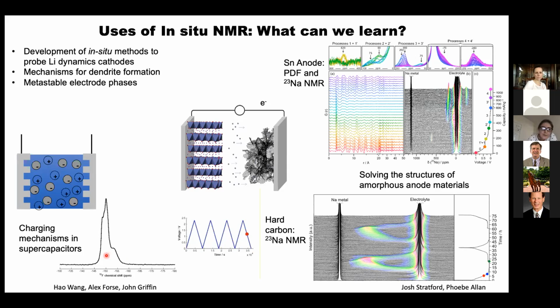And then you can also see that the peaks shift backwards and forwards as the voltage goes positive and then negative. And what you're watching is the change of the density of states on the carbons, and that then has an effect on the field felt by the NMR nucleus. And so we can be both quantitative, we can also say something about the electronic structures of the carbons, which is quite interesting. So let me now tell you a few more longer stories